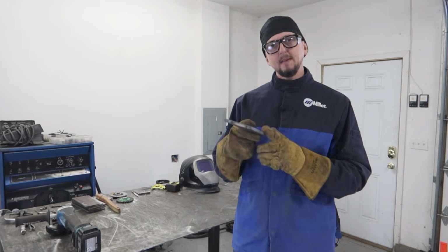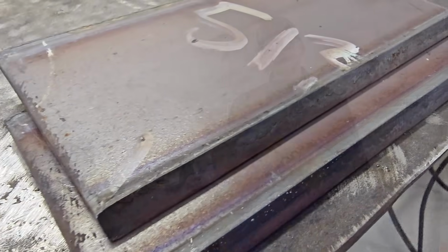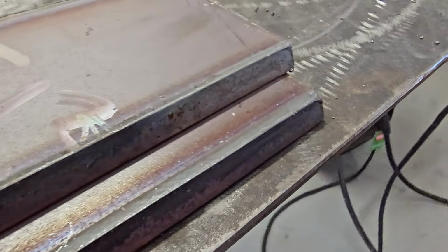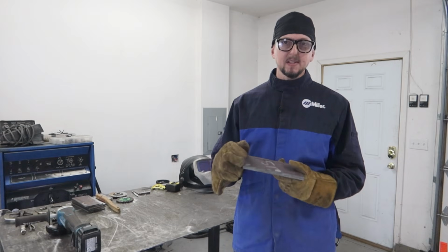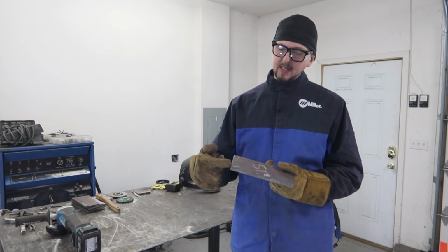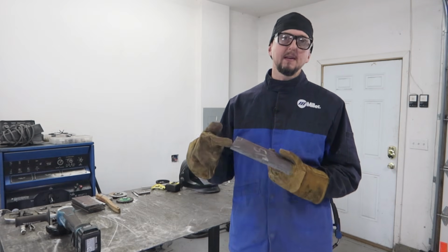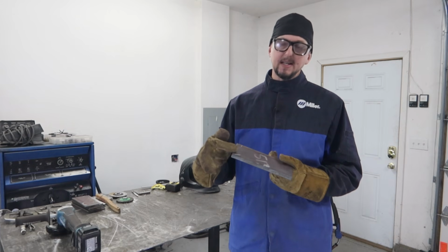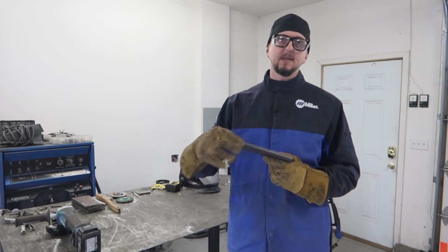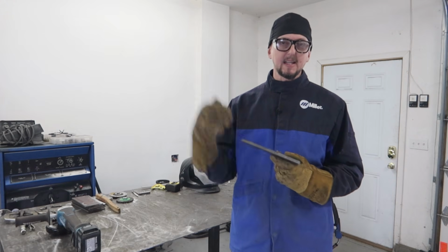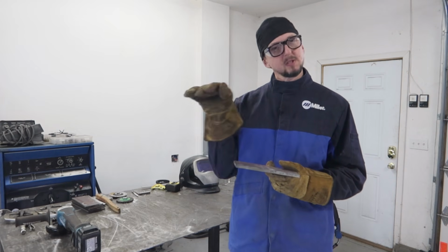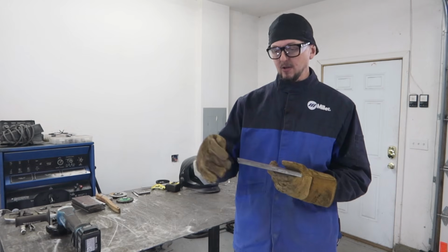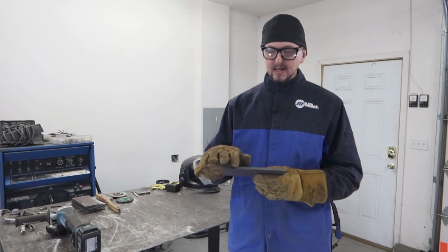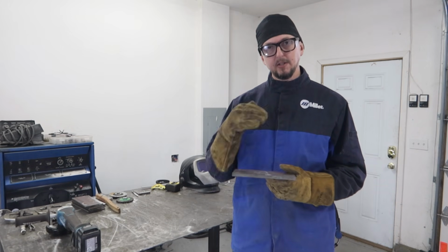All right, so we have our 3/8 plate already flame cut to a 30-degree bevel, but now we need to clean up the mill scale, and we want to clean up the mill scale at least about a ½ inch away from the edge on the face side of the plate. We want to clean up this whole bevel without affecting the actual angle of the bevel, meaning we just want to clean up that mill scale and the dross from cutting without actually gouging into the material and changing the shape.